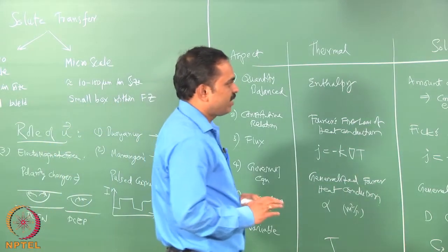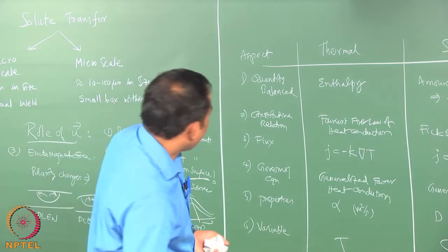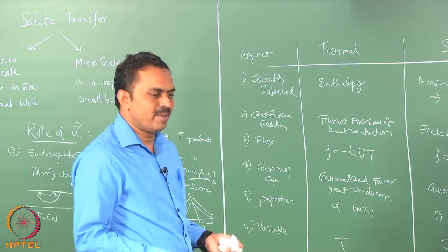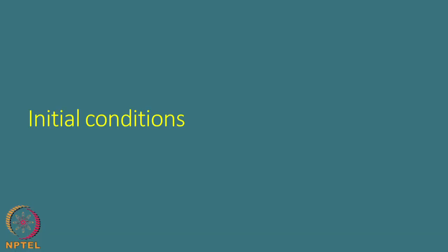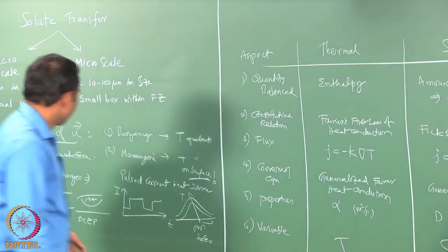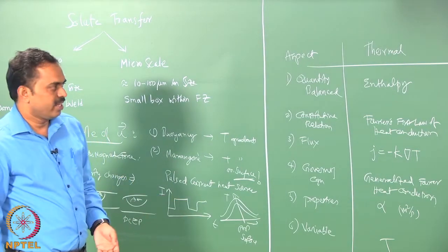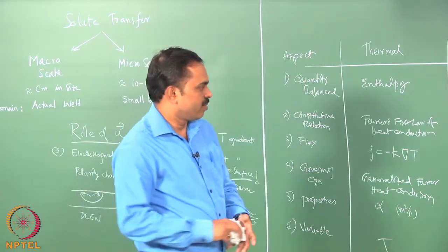Okay. So, because of that it is usually found that you may not have to solve for the macro scale distribution of mass, usually it is well mixed. But in case it is not well mixed, you could actually go ahead and do that also. For example, if you are using constant polarity and if you are not using pulsing current, surely there will be macro scale gradients that will be possible, and in such situations solving this may be necessary.